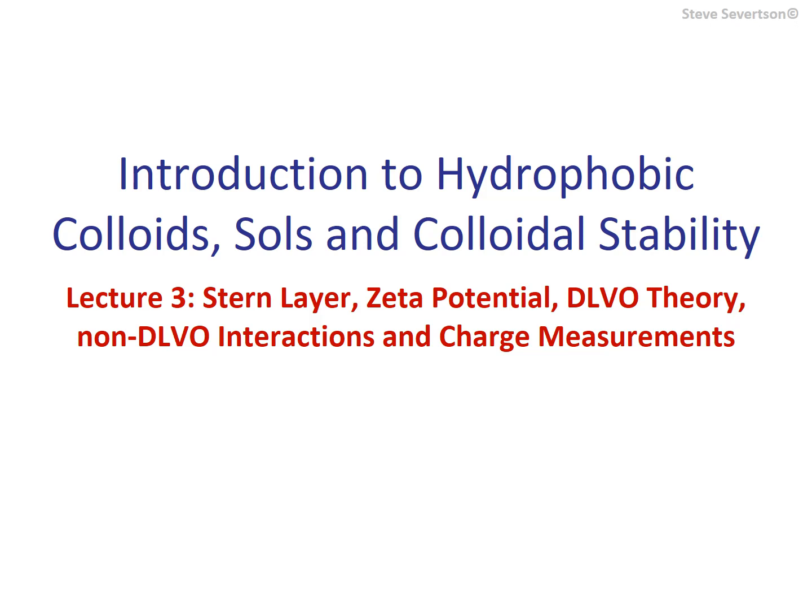In the previous lecture, the Gouy-Chapman model for the electric double layer was introduced. This involves several assumptions to simplify what is a complex system of charges. In fact, the Gouy-Chapman model is the simplest quantitative treatment of the diffuse layer that forms at charged surfaces. Our assumptions include a consideration of a uniformly charged flat surface of infinite dimensions, treating charges in the diffuse layer as point charges with concentrations determined by the Boltzmann principle, and limiting the role of the solvent, in this case water, to the influence of its dielectric constant. We also restricted the system to a single symmetric electrolyte and a low surface potential to limit calculations.